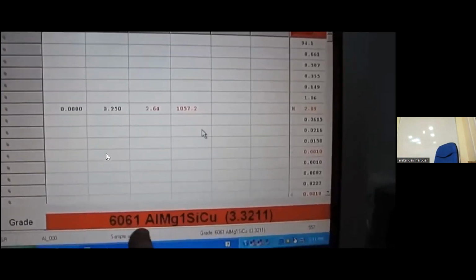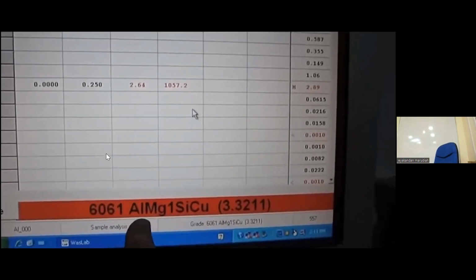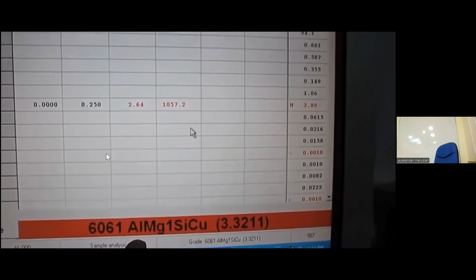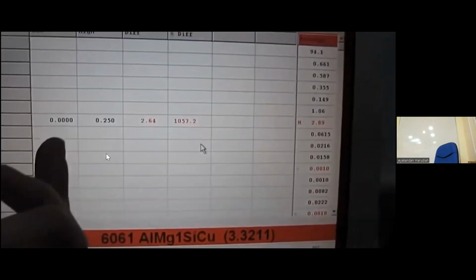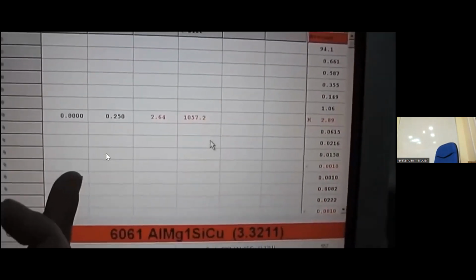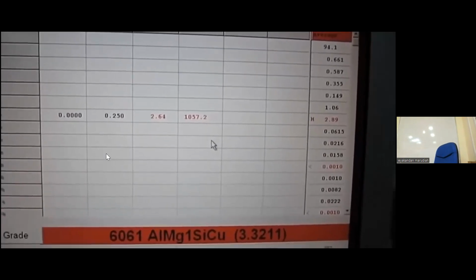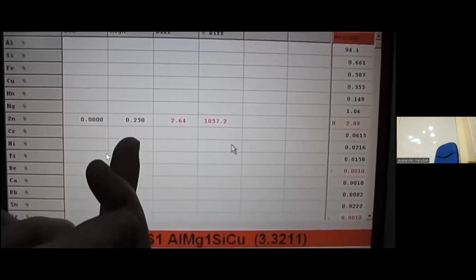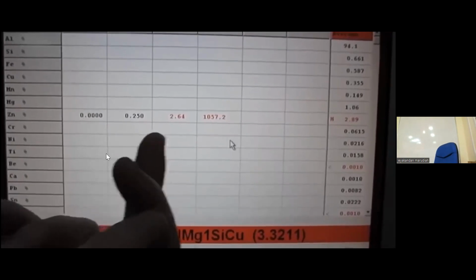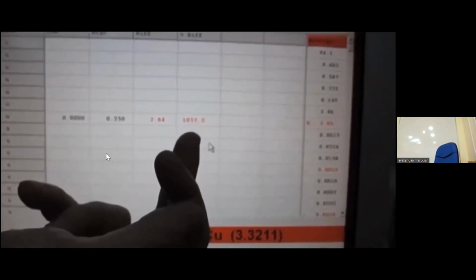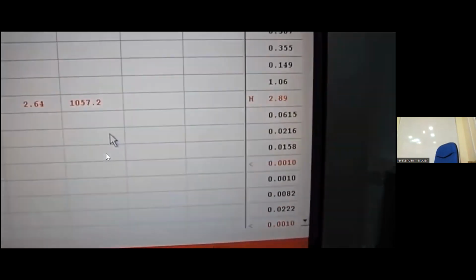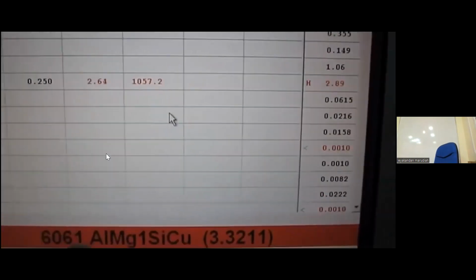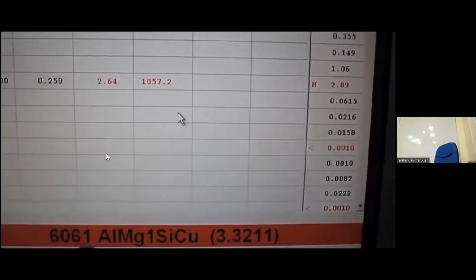Okay, now down the bottom here, we've got 6061 in red. Red means it is definitely not 6061. Above, it will show us where it is not 6061. The zinc should be between 0% and 0.25%. It's actually 2.64 points above where it should be. That's 1,000% too high. The average content is 2.89%. So we would actually reject this material as being 6061.